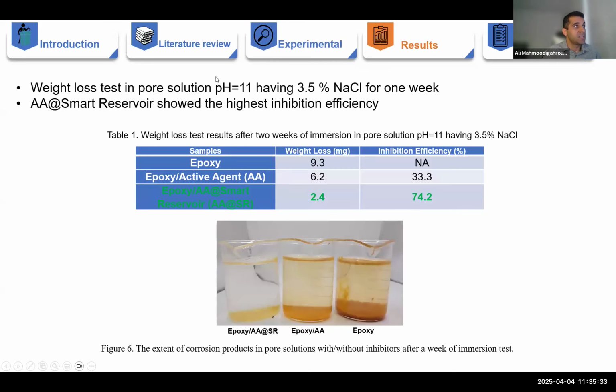What we did in weight loss test, we applied 3 different coatings on the surface of steel, including pure epoxy coating, which was control sample, epoxy coating containing a commercial active agent, and epoxy coating containing the same active agent, but here loaded inside a smart nano reservoir. And then we applied the coating on the surface of steel, and we submerged the sample in simulated carbonated concrete pore solution for a specific time.